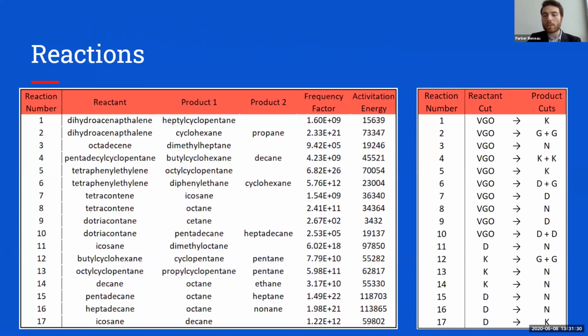And these are the reactions that we decided on. The first 10 reactions are our VGO feedstock going to our individual cut fractions. And then the latter reactions, 11 through 17, are the degradation reactions that we needed in order to best represent the curvature that you will see in our kinetics for diesel and kerosene at the higher temperatures. And as you can see in the leftmost chart, these are the frequency factor and activation energies that we decided on after doing our kinetic validation.